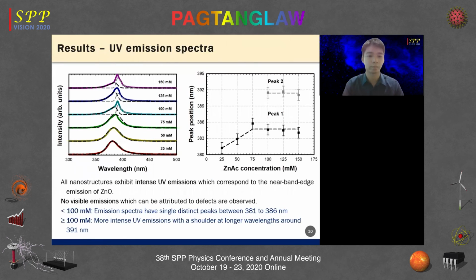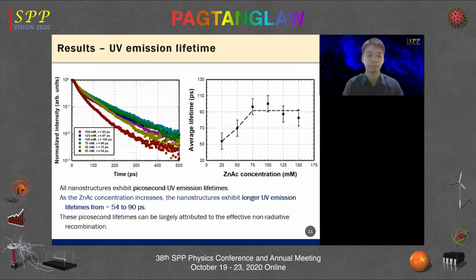This slide shows the emission spectra of the hydrothermal grown zinc oxide nanostructures, and all the nanostructures exhibit intense UV emissions which correspond to the near band edge emission of zinc oxide. No visible emissions which can be attributed to the defects are observed. Examining the UV emissions, we can see that for concentrations below 100 millimolar, the emission spectra have single distinct peaks between 381 to 386 nanometers. On the other hand, for concentrations above 100 millimolar, we observe more intense UV emissions with a shoulder at longer wavelengths located at around 391 nanometers.